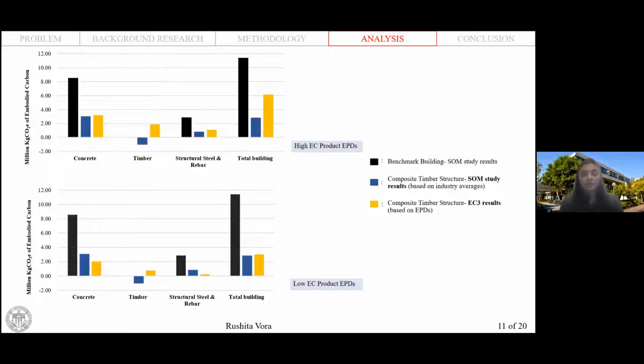Now, from the top graph, it can be seen that all the materials that were assessed using the EC3 tool have a higher impact than the industry averages or the published results. Whereas on the bottom graph, all the materials have a lower impact. This assessment shows that the industry average may not always provide a very accurate and clear picture, as it is probable that the product that is eventually assigned to the material may perform worse than the assigned industry average, which can lead to inaccurate and misleading results.